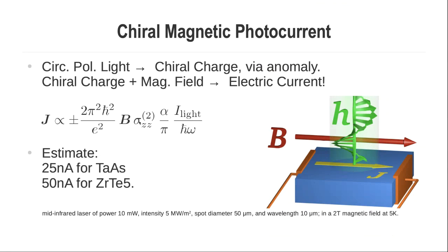It could be a two-dimensional surface current density, right? Yes. So, actually, I should have said that directly. This number is a two-dimensional current density that's integrated over the depth over which it's generated. And this doesn't depend on the spot area, it only depends on the spot width. So you get an expression which doesn't depend on the conductivity if you integrate it over the depth of the sample. So this is linear current density on the surface. That's what it is. I'm not sure if I explained that correctly, but yeah.